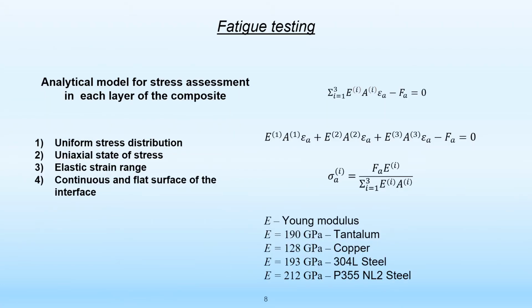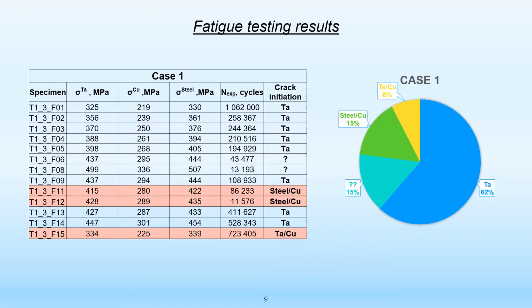As the tests were carried out in a force-controlled manner, for easier comparison, a simple analytical model was used to assess maximum stress level in each particular composite layer. Several assumptions had to be made, such as uniform stress distribution, uniaxial state of stress, elastic strain range, continuous and flat surface of the interface. On the right, you can see basic force equilibrium equation, adjusted for the presence of 3 layers of the composite, and its transformation.